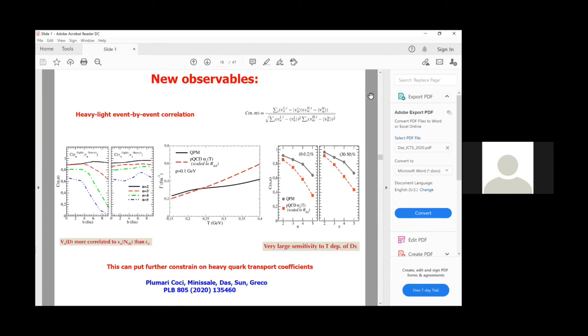temperature. So this temperature dependence, as we can see, in one case, the pQCD case, the interaction is strong near the early stage, whereas in the quasi-particle model, the interaction is much stronger near the quark hadron transition temperature. Due to this different domain being dominant, this heavy-light correlation coefficient is sensitive. Because as we can see also in this earlier plot, the VN-VN correlation coefficients are strongly correlated, and they are really sensitive to the temperature dependence.